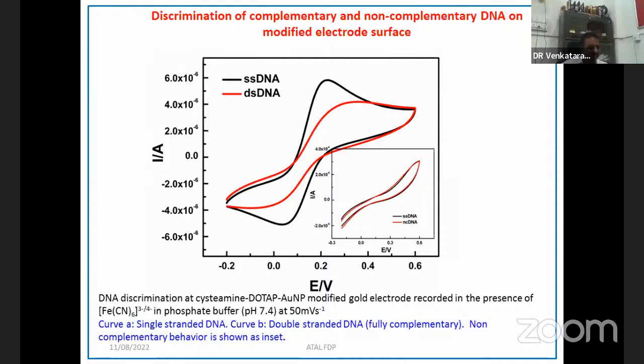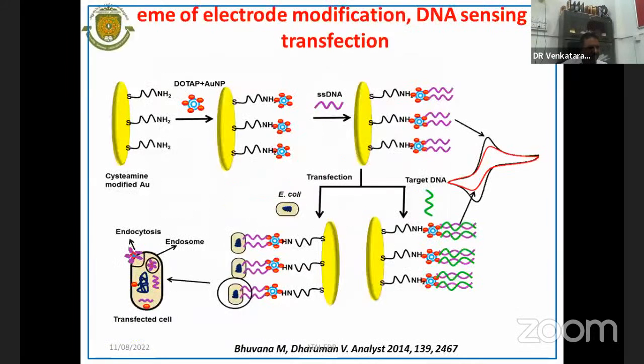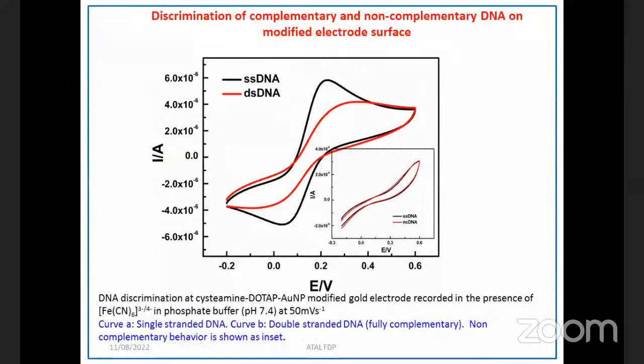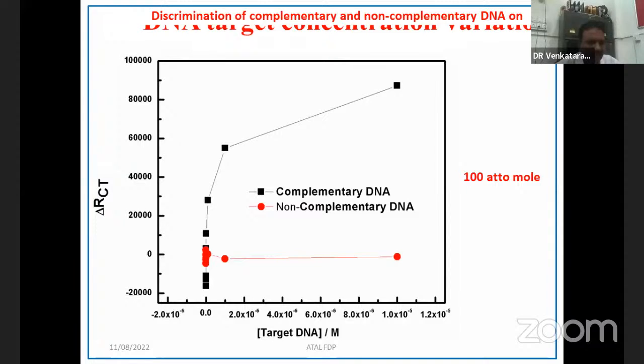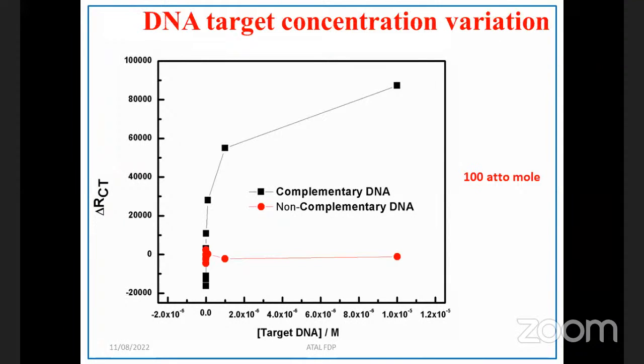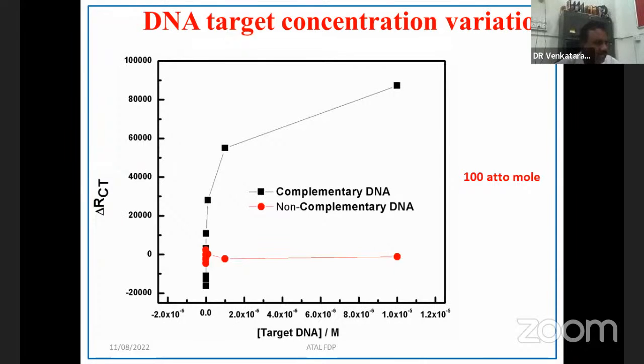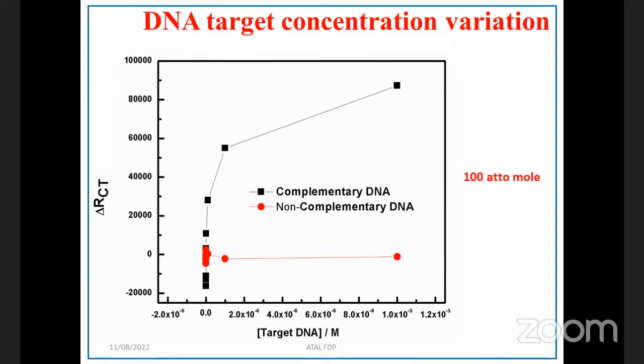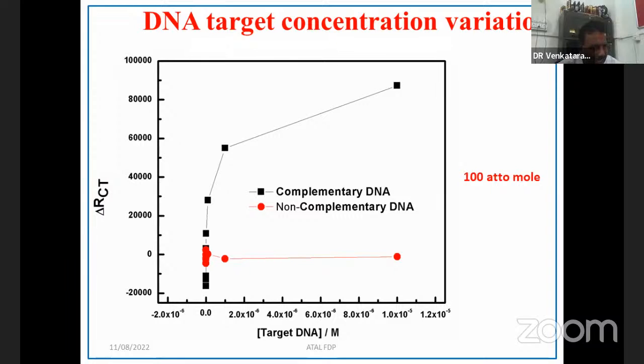We use two different techniques. One is cyclic voltammetry and another one is impedance. What we do, we calculate the resistance between the single strand and the double strand difference, and we plot it as a function of concentration. What we see was the complementary gave higher resistance than the non-complementary, and the lowest detection of the helical formation was detected at 100 attomolar.